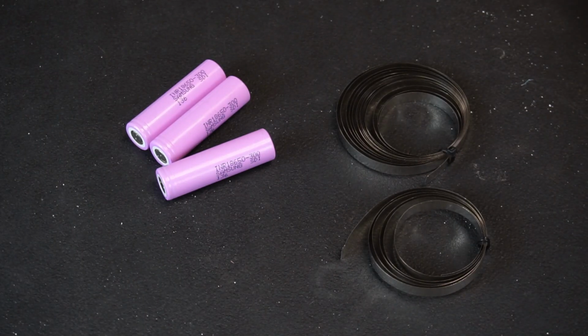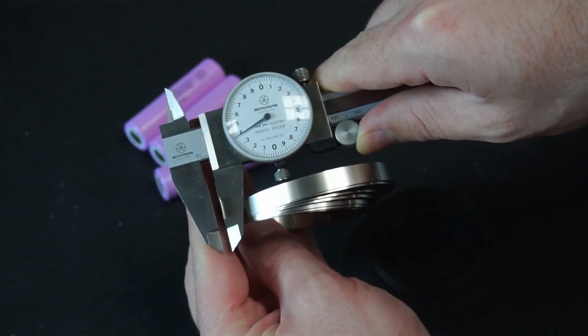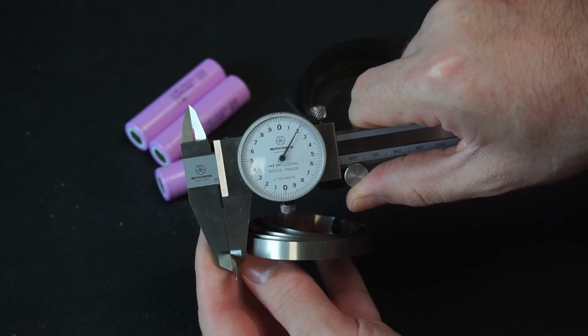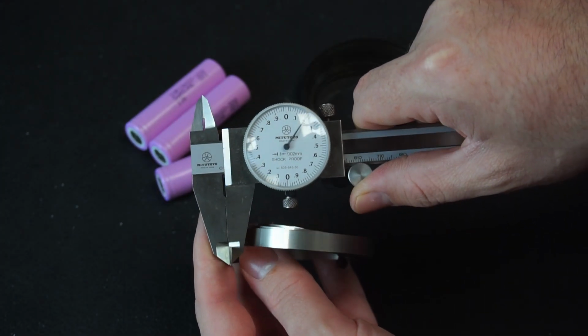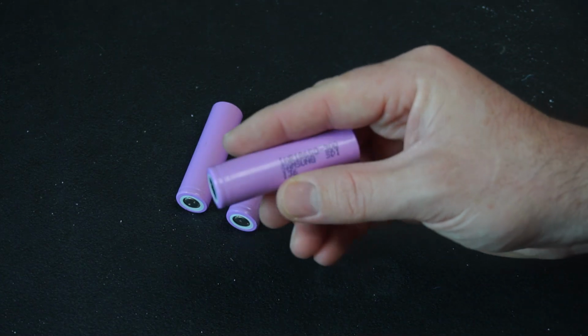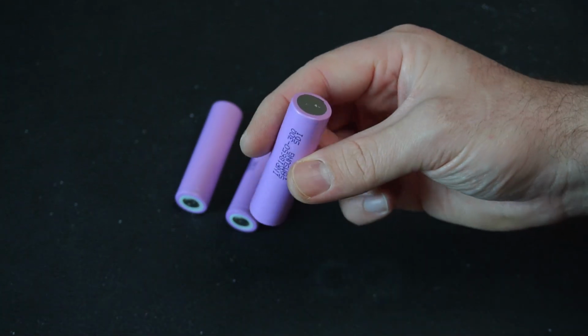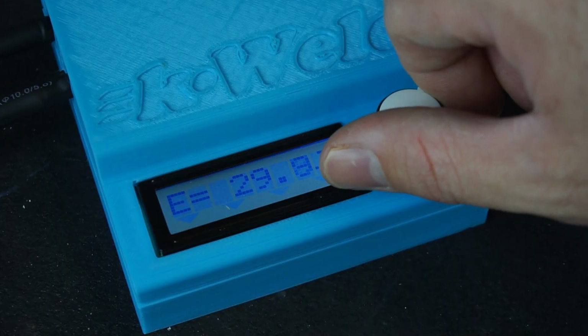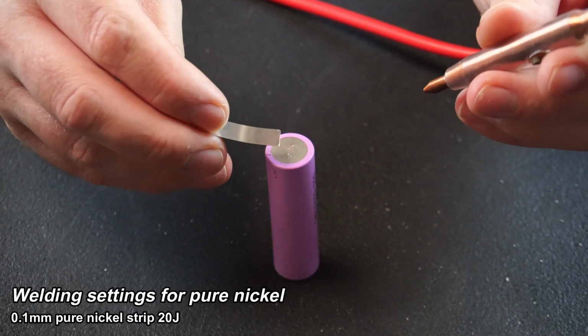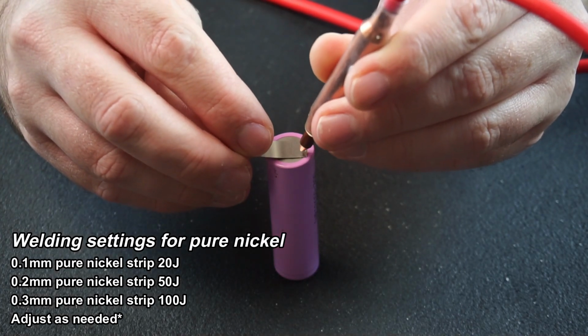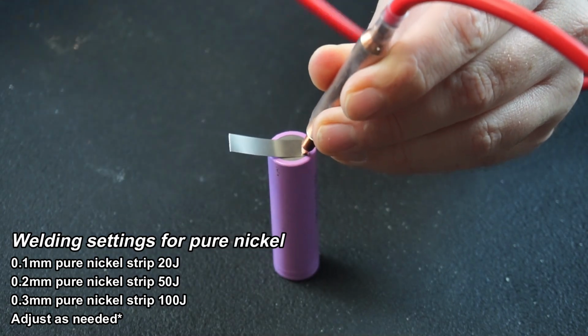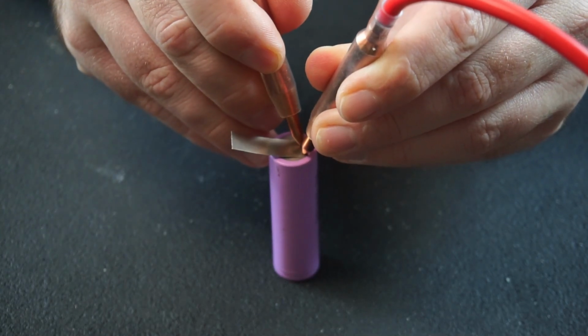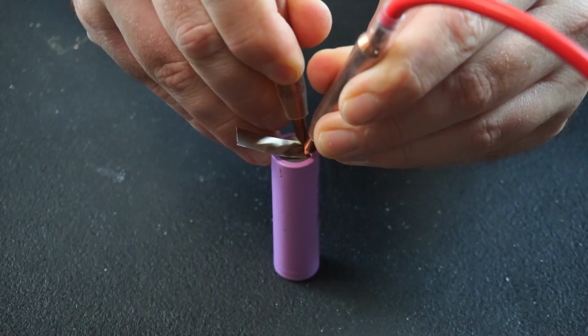I bought two different pure nickel strips to test with. One is 0.15 millimeter and the other is 0.2 millimeter thick. I grabbed a few old 18650s that have expired so I could mess around with various weld settings. I set the welding pulse to 30 joules and used a piece of 0.15 millimeter nickel strip. I firmly pressed the electrodes into the nickel strip and pressed the foot pedal, and I have to say the quality of welds look excellent.